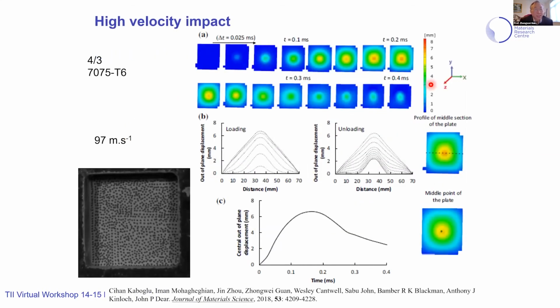This is high velocity impact, close to 100 meters per second. We have DIC recording the back face displacement field at different times. We can see the impact event start, then reach a peak, and then try to bounce back. This one is not fully perforated.